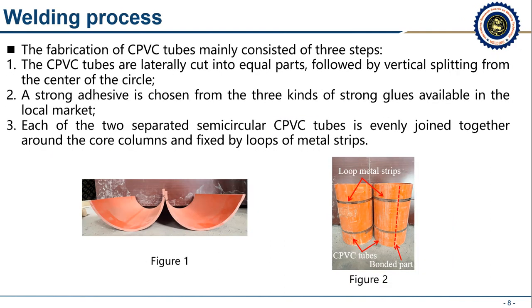Due to the high strength and brittleness of CPVC tubes, they can easily be split into 2 semicircles without any deformation. The fabrication of CPVC tubes mainly consisted of 3 steps. The CPVC tubes were laterally cut into equal parts, followed by vertically splitting from the center of the circle. A strong adhesive was chosen from the 3 kinds of strong glues available in the local market.